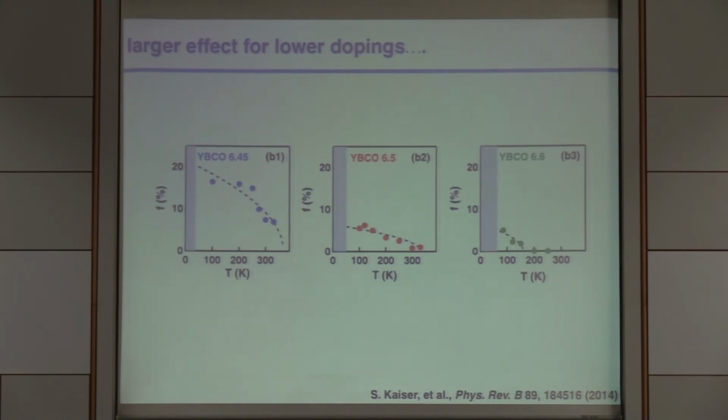No. Below TC, you have a plasma edge at 2, and you see it at 3. I don't know what 2 and 3 are, but let's say. Above TC, you have a plasma edge at 0, because the superfluid density is 0, and then you get a plasma edge at 3, which emerges like Venus out of the waters. You didn't have it before, okay? So that's the observation. The percentage increase is such that you recreate the plasma edge that you observe, give or take 50% of the position in the same material at 0 temperature. It's not that you find an edge in a strange place.